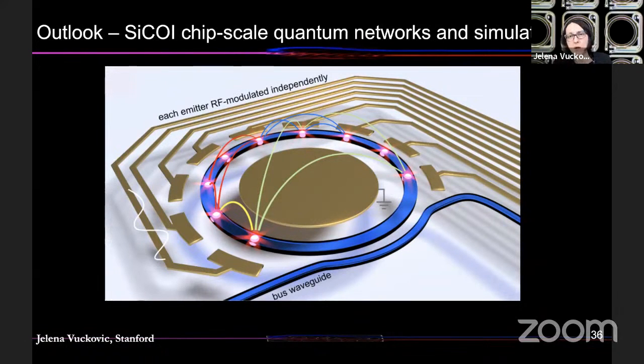We're also working on the problem of bounds for inverse design, which means, what is the minimum footprint that you need to start with to get a particular efficiency. Those bounds would tell you more about the landscape before you even start running optimization. So it's not a trial and error. Right now there is a trial and error, but we made it fast, so you don't really need to wait a long time to get feedback. You have feedback after about 10 or 15 minutes, and you know whether you need to restart and reinitialize to get into a different solution.